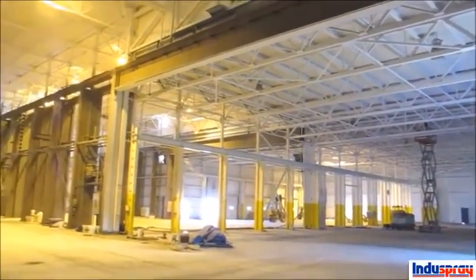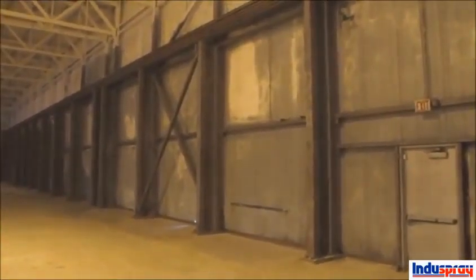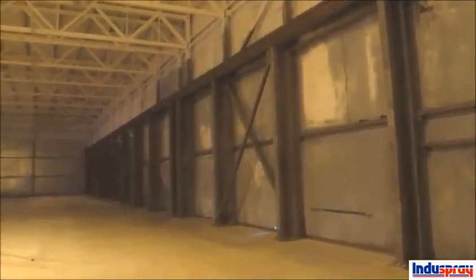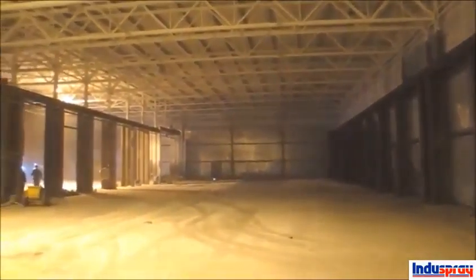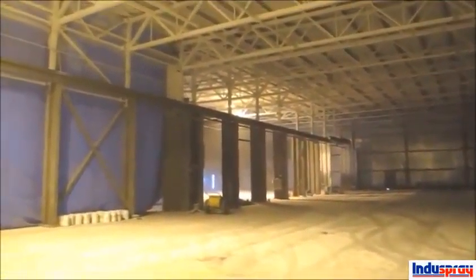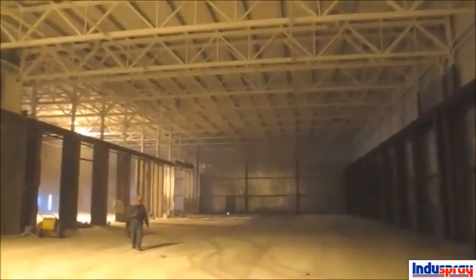We've sandblasted this whole room out and primed up the ceiling. The steel was all blasted to SSPC-SP6, and the decking on the ceiling and the perimeter walls were brush blasted, commercial blasted, so the coating will last a long time. I couldn't take any pictures of here before because it was just too dark — very few lights in here — but now that the ceiling's painted white you can actually see pretty well.